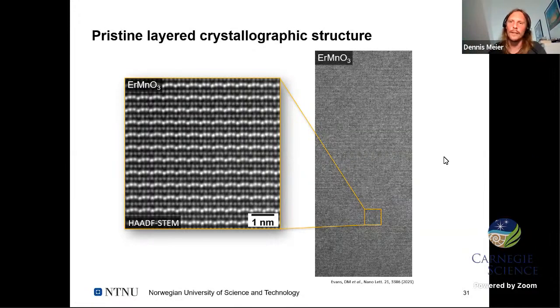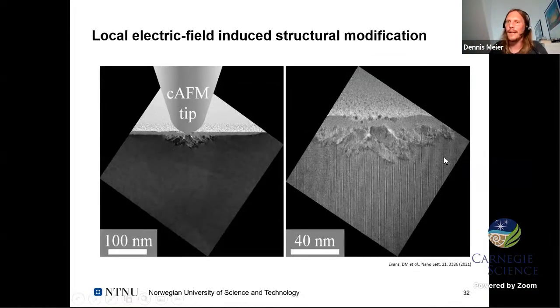But what we can do is we can apply an electric field and, at first glance, ruin this structure. What we did here is we placed an AFM tip, applied 60 volts for 5 seconds, and you see that right under the tip, the structure has changed. How the change looks like, we can see best when we now zoom in, and that's done here.